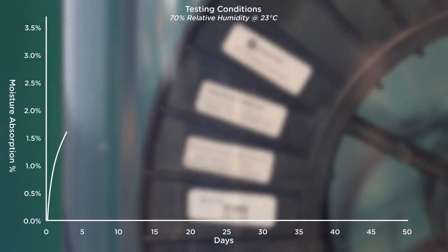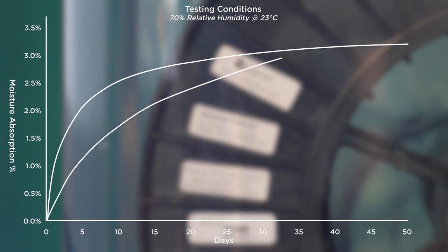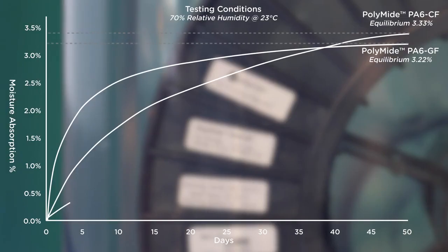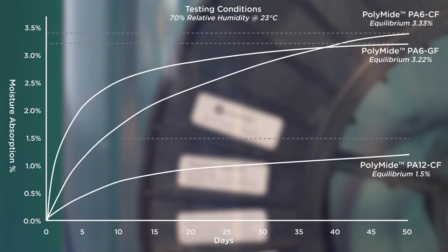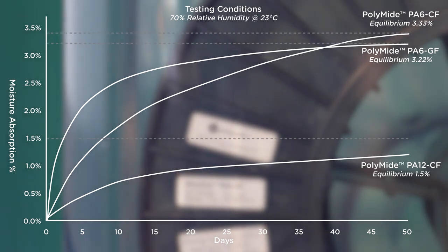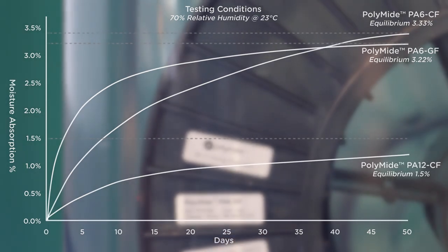Nylon 12 is much less sensitive to moisture absorption, which means that the filament is more stable, more predictable, and generally easier to print and to store. PolyMide PA6-CF will reach moisture equilibrium at 3.33%, which is the point at which the part cannot absorb any more water molecules from the atmosphere. In comparison, PA12-CF reaches equilibrium at 1.5%, absorbing less than half the moisture of the nylon 6.